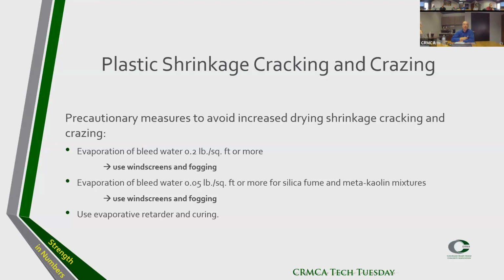Precautionary measures to avoid drying shrinkage cracking and crazing. Well, the next slides are going to show the graphs, but if the evaporation of bleed water is 0.2 pounds per square foot or more, then we should use windscreens and fogging. If the evaporation of bleed water is 0.05, which is pretty low, or more for silica fume and metakaolin mixtures, then you need to use windscreen and fogging, or use evaporative retarders and curing.